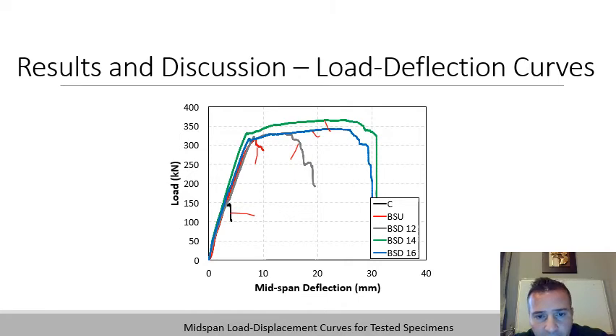can see it failed at a very low midspan deflection, so the ductility is very low. We are able with the anchors to change the structure from failing in a brittle mode at around 325 kilonewtons to a slightly higher load, but look at the ductility the beam is exhibiting before failure. This means that I changed the failure mode from shear to flexural.